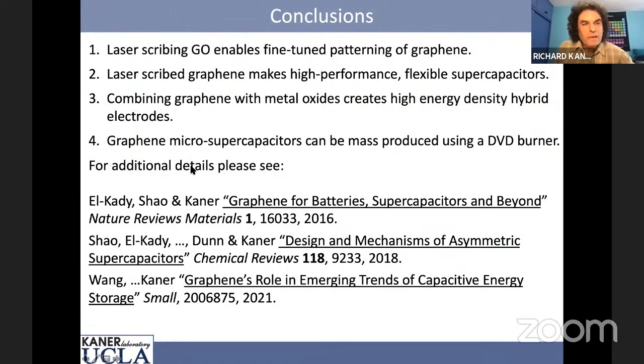All right, so basically, I hope that I've showed you that laser scribing enables you to make fine-tuned patterns of graphene. You can make high-performance supercapacitors. You can combine with metal oxides, and we just looked at a few, but in the literature we published on half a dozen different metal oxides to make these hybrid capacitors. And you can mass produce these with a DVD burner.